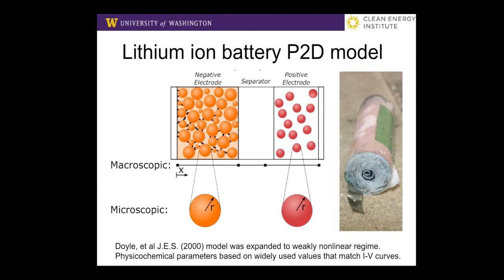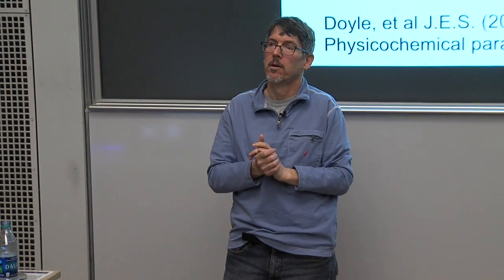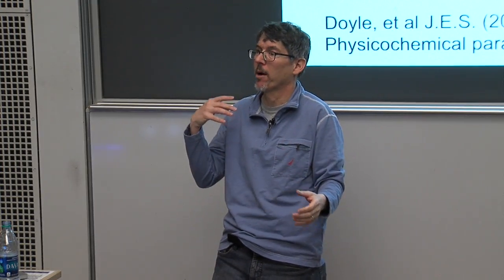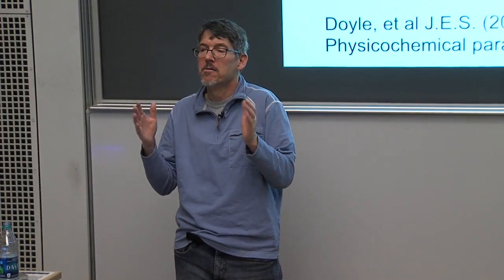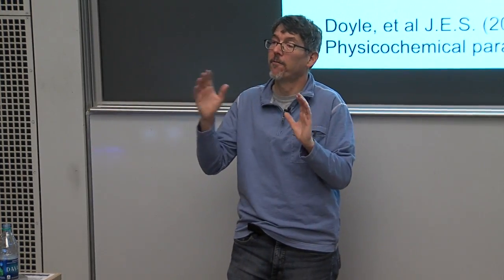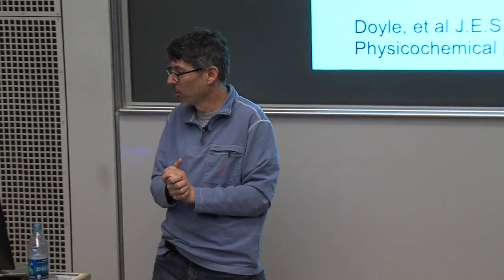And a model like this, which is known as the P2D, pseudo two-dimensional model, because it's got particle dimensions and cross-section info, has roughly, depending upon details of what you do, roughly 20 physical chemical parameters to represent charge transfer, to represent diffusivity of ions, conductivities, and could be from 5 to 10 geometric parameters that you could go in and measure if you knew them for most of these electrodes. So that's what is in a typical model.